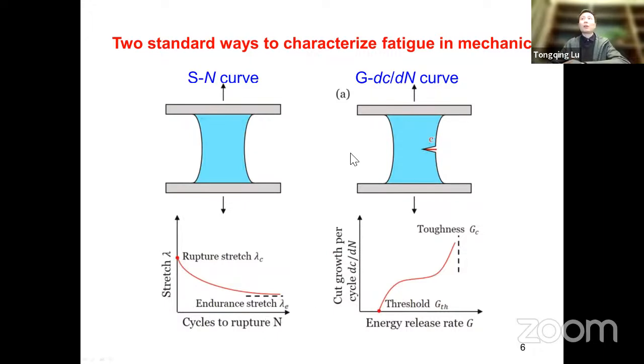The other way is we make a cut in the sample and apply a load, and we represent the load with what we call energy release rate. And we measure the cut growth per cycle. So we cyclically load it and we record how fast the cut will grow and record this curve. So in this talk, we will use this method to characterize fatigue.